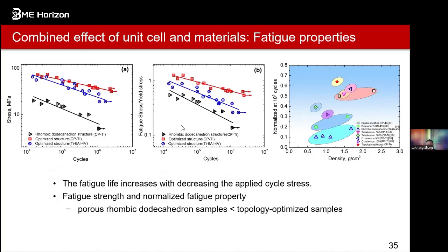For example, here the left two figures show the fatigue SN curve of the topological, optimized, and the rhombic dodecahedron structures. The fatigue life increases with decreasing applied cycle stress. Of course, the fatigue strength and the normalized fatigue properties, that means the fatigue stress divided by the yield strength of the rhombic dodecahedron one, you can see it's significantly lower than those of a topological one. So that's why the topological one has a better fatigue life and fatigue property.